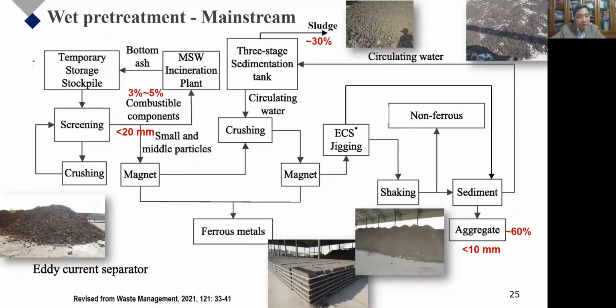Before utilization, pretreatment is necessary to adjust the size distribution, remove unburned organic matter, and recover ferrous and non-ferrous metals. There are mainly 2 kinds of pretreatment processes for bottom ash, wet and dry methods. Because bottom ash is usually water quenched and removed from incinerators, wet pretreatment has been widely used in China. This schematic diagram shows a typical wet process. The unburned substances are fed back into incinerators. By wet crushing, magnetic jigging, and shaking separation, ferrous and non-ferrous metals can be recovered, and aggregate, usually with size less than 10 millimeters, is obtained.